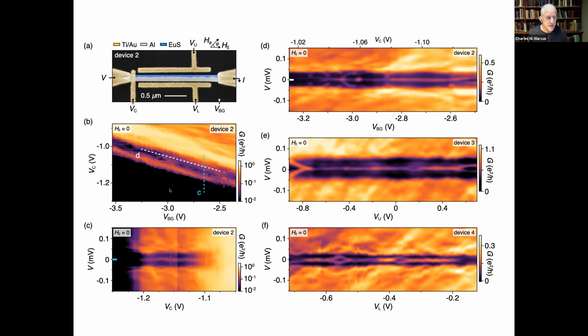Let's change as a function of a back gate, which changes the density inside of the wire, and a cutter gate, C stands for cutter, which changes the depletion of the tunnel barrier. We can follow a kind of iso contour line called D, or we can follow a cut along C. Let's follow the contour line along D, where you've compensated the change in backgate with a change in cutter so that you follow the same physics along this line.